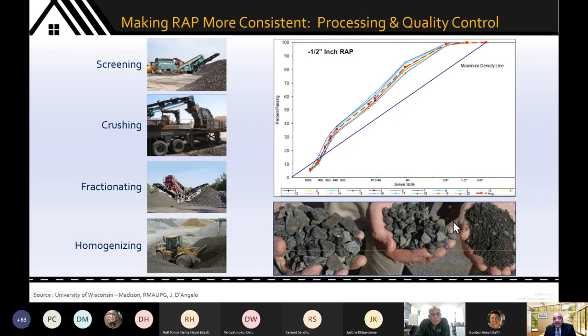And the reason for that is, in general, it is found that if you want to move to higher and higher RAP percentages, you need to be able to fractionate the material. In other words, the number of fractions that you make of your RAP will limit the amount of RAP that you can put into your mix. And we'll talk about reasons why later on.